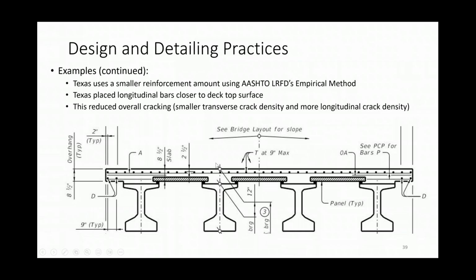The other change they made is that the very top layer of rebar, as you see in this cross section, is the longitudinal rebar. So the longitudinal rebar, they place it closest to the top surface. And the reason for that, again, is that their prevalent cracking was in the transverse direction, so the longitudinal bars restrain those cracks better. And this did help them reduce overall cracking, even though, of course, they got much smaller transverse cracks, but they got more longitudinal cracks, but overall they did see reduced cracking. So it seems like they're happy with these changes.